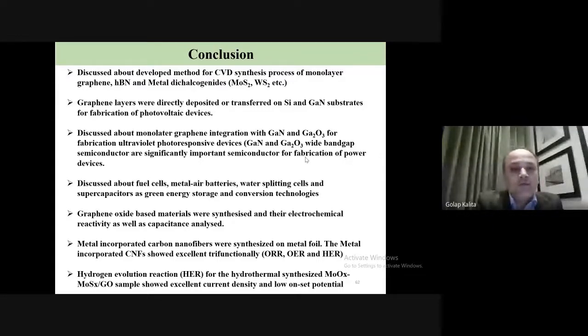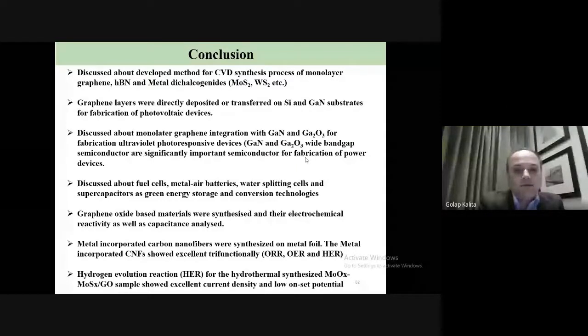Then we synthesized some metal incorporated carbon nanofibers, which show tri-functionality: ORR, OER, HER. All three reactions we can observe in this kind of catalyst. Then I showed some MoOx and molybdenum oxide or sulfide heterostructures, the material synthesized by hydrothermal process, which shows excellent hydrogen evolution reaction with low onset potential and excellent current density.